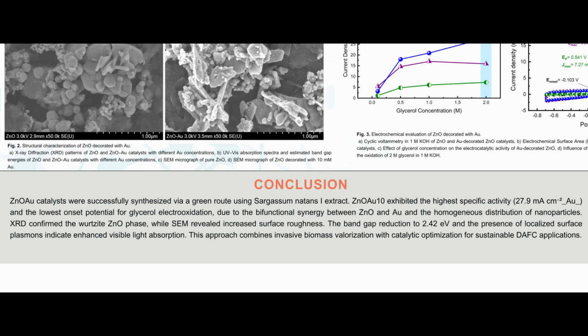Conclusions. We successfully synthesized zinc oxide gold on carbon catalyst via a green route using Sargassum natans 1 extract, producing defect-rich zinc oxide that anchored gold nanoparticles effectively. The zinc oxide gold 10 millimolar composition exhibited the highest specific activity and the most favorable onset potential for crude glycerol electrooxidation in alkaline medium. The results showed that noble metal loading and performance are not linearly related. Optimal activity depends on balancing surface area with strong metal semiconductor synergy. This work not only advances electrocatalyst design, but also demonstrates the value of converting invasive biomass into high-performance materials, addressing environmental and energy challenges simultaneously.